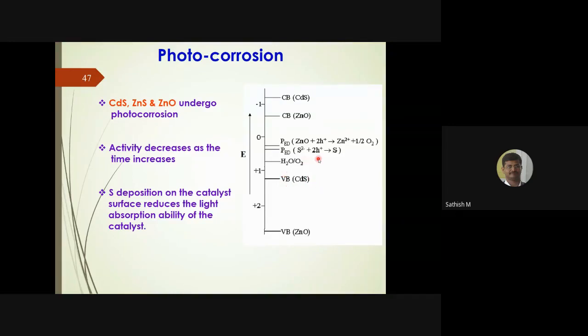But unfortunately, your sulfide S2- ion will take two holes, and then it will deposit as sulfur. So this potential falls in between the valence and conduction band, particularly close to the valence band. Because of this, what will happen is when you excite an electron from the valence band to the conduction band, you will produce an electron here. You will have holes here.